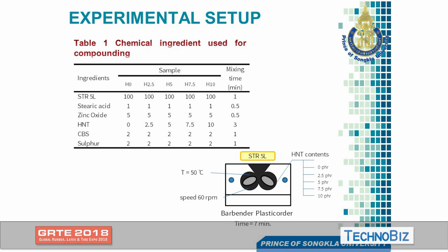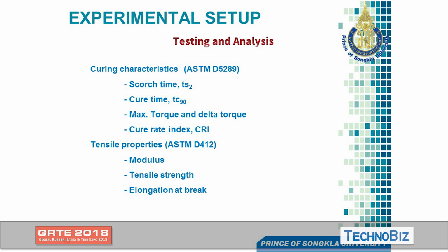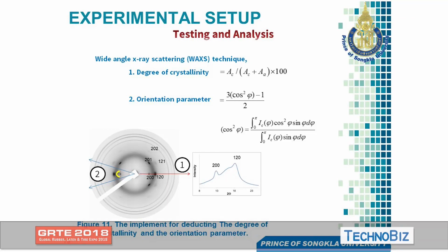Here are the formulations and preparation. The composite was prepared in an internal mixer at certain temperatures and a certain rotor speed, and the loadings were 0 to 10 phr. As for the testing and analysis, we study the curing characteristics and tensile properties. The next one is wide-angle X-ray scattering, where we study the degree of crystallinity and orientation parameters to see whether the alignment is isotropic or anisotropic.